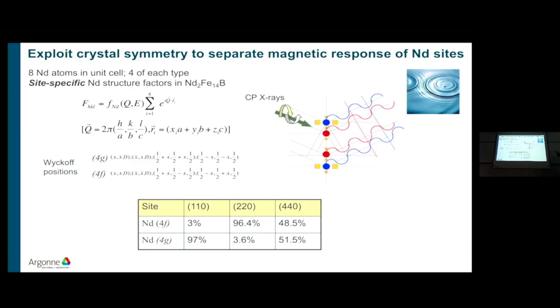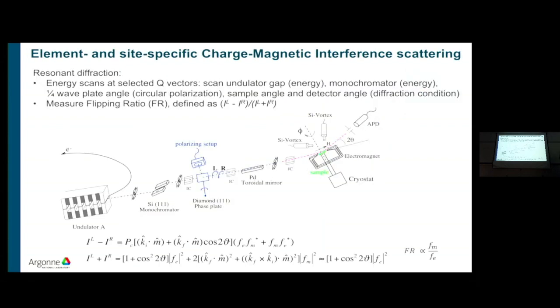So it's basically just Bragg condition. So this is a ferromagnet, so the magnetic scattering will be on top of the charge scattering. So in an experiment, we can put the sample in a magnet. Back to your question, put the sample in a magnet, so we can flip the direction of the magnetic field if you want to do a hysteresis loops or something.